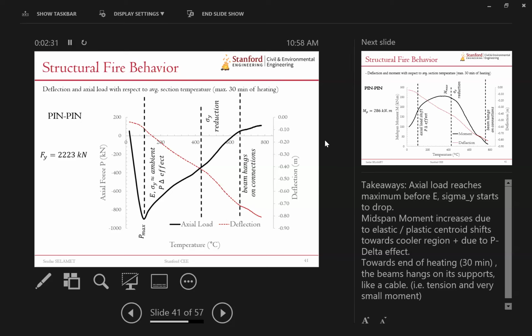Just mind that the axial capacity of this beam at ambient temperatures is about 2,223 kilonewtons. So we're not tapping that at all. The beam has not yielded in axial load for this 30 minutes of fire loading. What happens is that Young's modulus and yield stress start to drop actually after this. Young's modulus will drop after 100 degrees Celsius of the structural temperature, and the yield stress will drop at around 400. Then you will get this maximum axial load, and then that axial load will start dropping because the deflections are getting excessive, not because you started cooling.